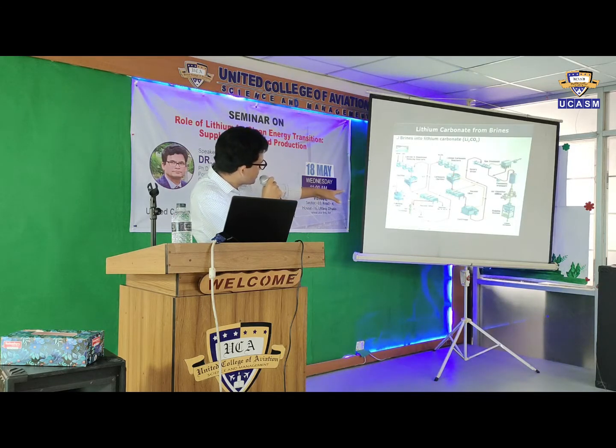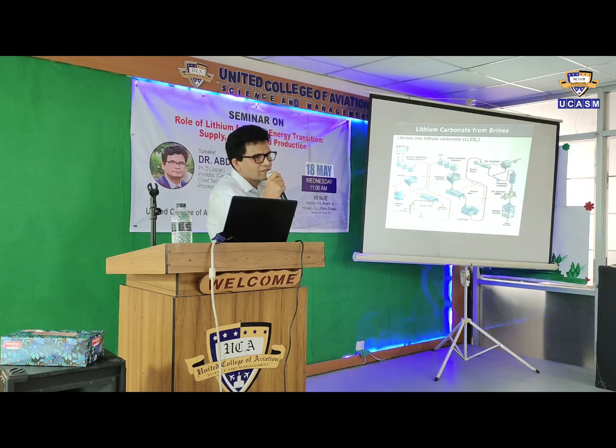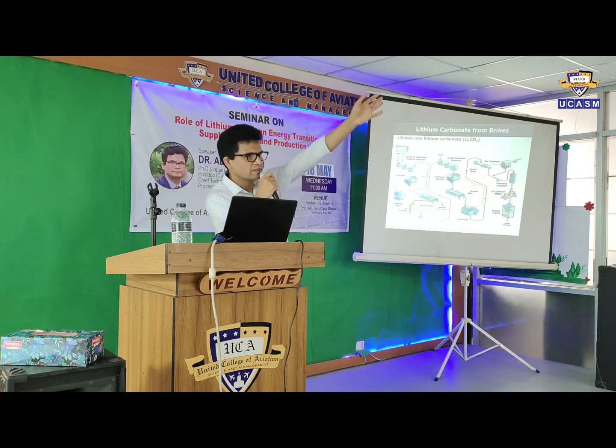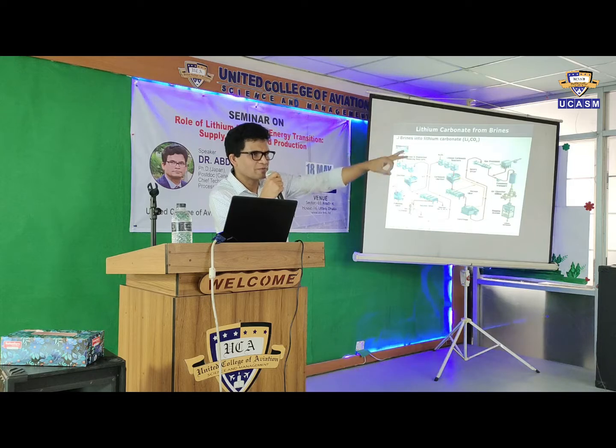Then, once we precipitate the impurities, we have the lithium. Finally, we have the impurity-free, pure lithium solution. Then we use sodium carbonate, because our target is to produce lithium carbonate. So we are using sodium carbonate to precipitate lithium carbonate. Now your question might be, why do we use sodium carbonate? Because in the periodic table, lithium and sodium are very close to each other. So you are precipitating lithium carbonate by sodium carbonate.